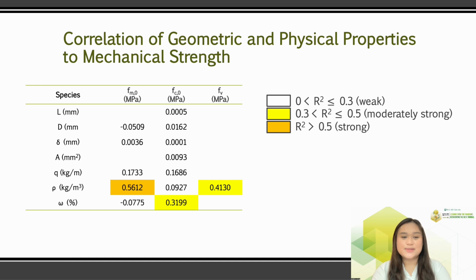Simple linear regression was used to assess the relationships between the geometric and physical properties to the mechanical properties of bamboo. The performance of the model was determined based on its coefficient of determination value, classified in 3 levels of correlation. The results indicate that the bending strength has a strong correlation with density, while the compressive and shear strengths have a moderately strong correlation with moisture content and density, respectively. The geometric characteristics and mass per unit length of the bamboo show weak correlation, which indicated that all 3 strengths are relatively independent of these properties.